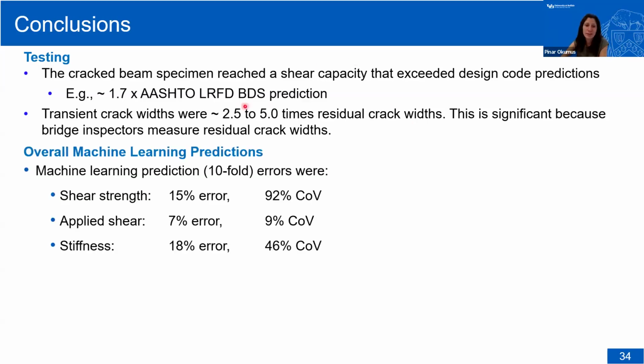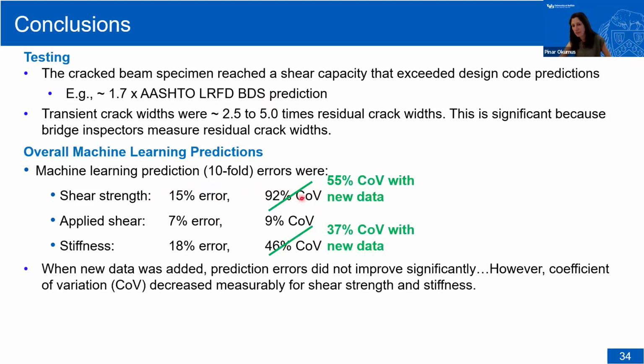Overall machine learning prediction errors, as I presented earlier, are shown here. So I show the error and the coefficient of variation. This is before we tested the new beam. After we added that new beam data, we managed to decrease the coefficient of variation for shear strength and stiffness predictions. It didn't do much for the error. And it didn't really affect the applied shear predictions, which were already good to begin with. And that shows that the variety of data that you could add to the data set could make a difference, because we have somewhat different data than the majority of the data in the literature.